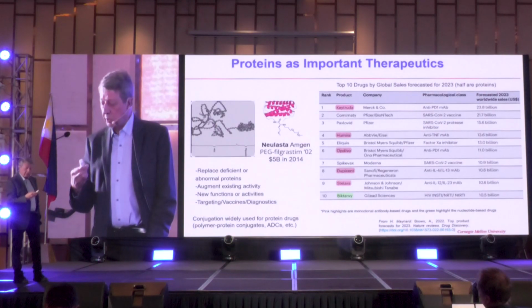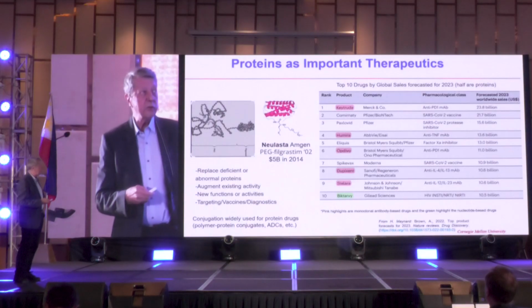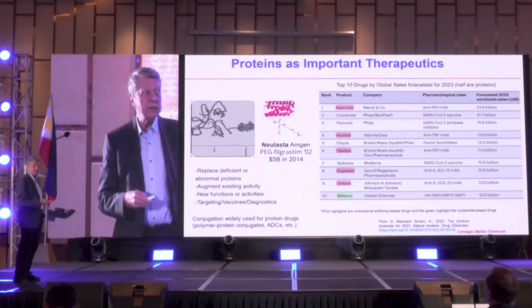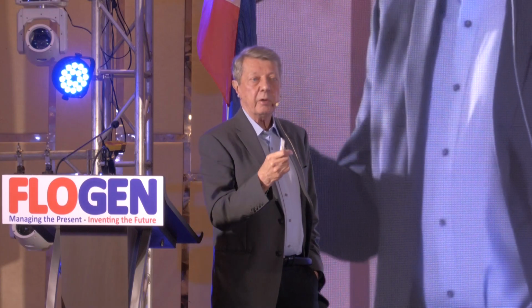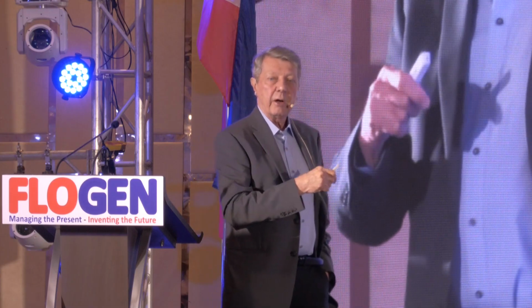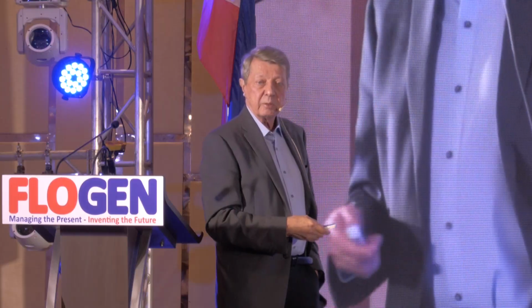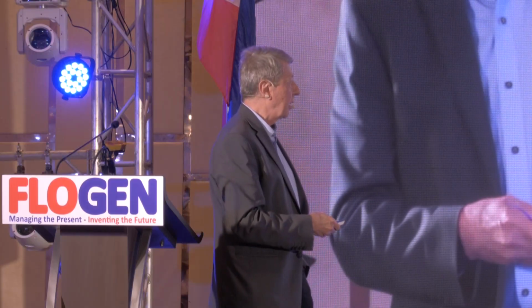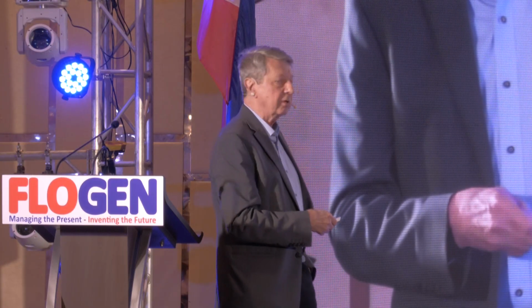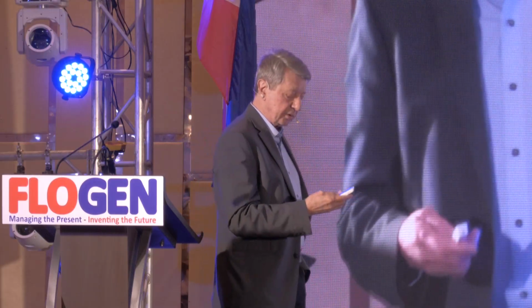So what they did, they conjugated this filgrastim with polyethylene oxide, 20,000. Now it has a 40,000 molar mass and is not cleared through the kidneys and can circulate in the body for 3 weeks. So if you compare every 2 hours or every 3 weeks, obviously people would prefer the second option, and therefore you could see that already 10 years ago, it was a market of $5 billion.